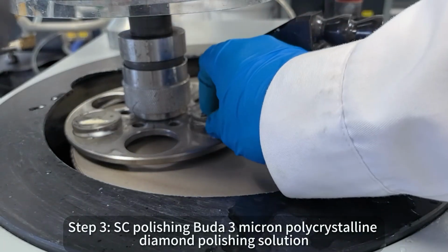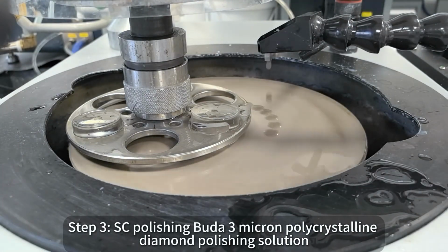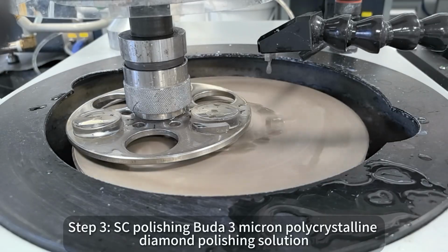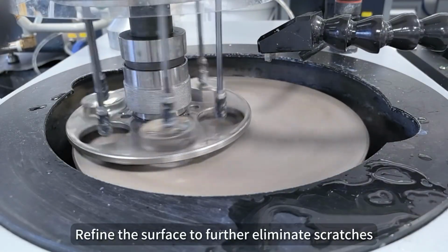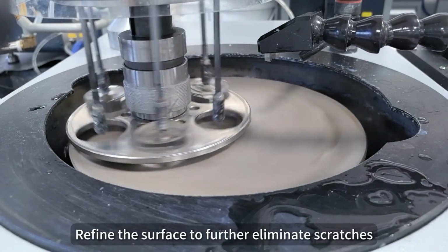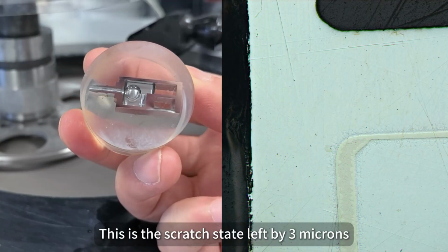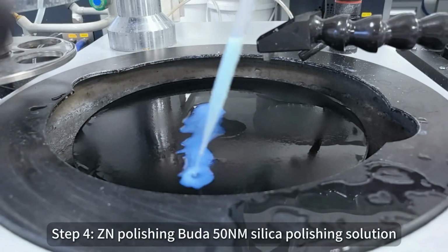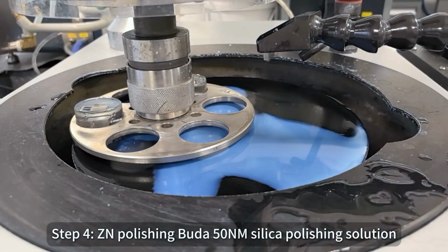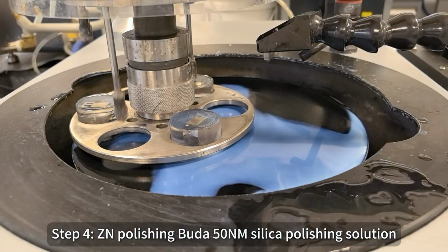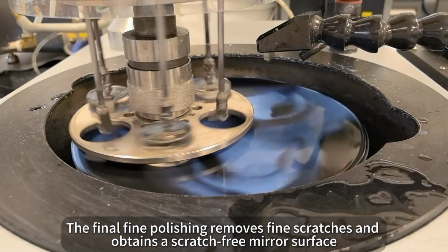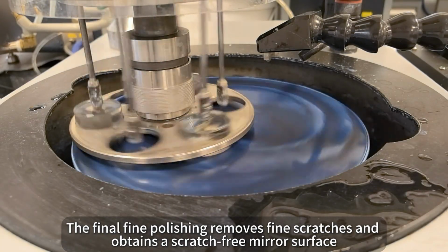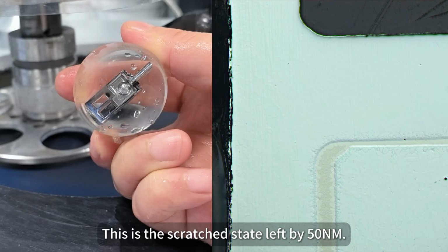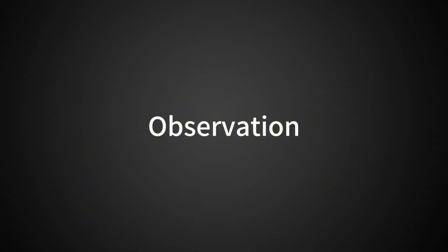Step 3. Polishing cloth with 3-micron polycrystalline diamond polishing solution. Refine the surface to further eliminate scratches. This is the scratch state left by 3 microns. Step 4. Polishing cloth with 50 nm silica polishing solution. The final fine polishing removes fine scratches and obtains a scratch-free mirror surface. This is the scratched state left by 50 nm.